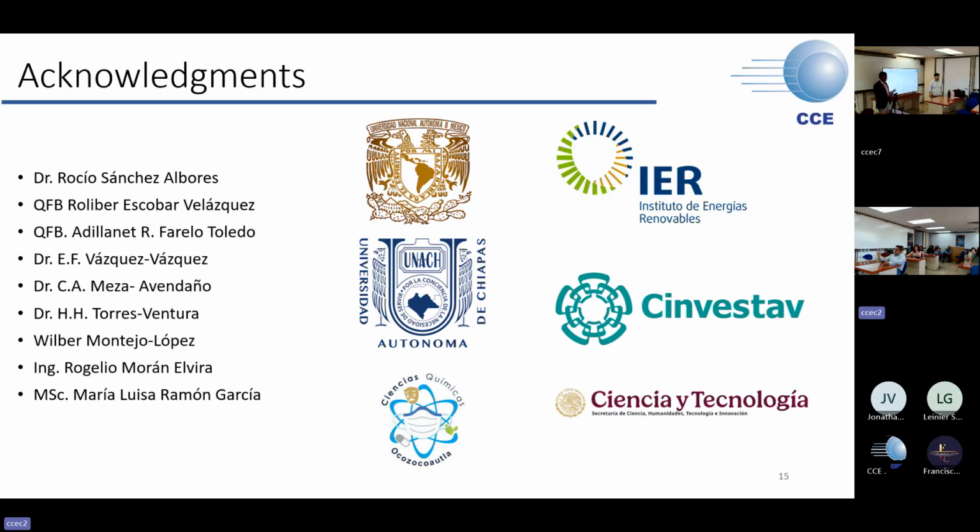What kind of degradation have you observed in the two types of membranes? Actually, we have some troubles with the stability of the membranes. If they are in liquid water, they can keep working over time. But if you leave them in a dry condition, some fractures become visible. So if we would like to reuse them, we have to store them in liquid condition.